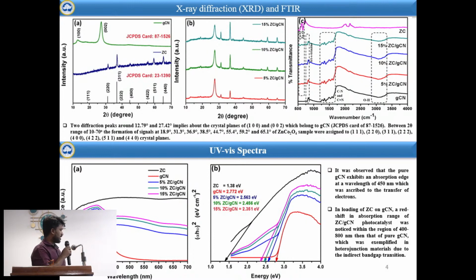And we have also obtained the optical property with respect to the UV analysis. We obtained the absorbance spectra, through which we calculated the Tauc plot, and from it we can obtain the band gap energy of the material. We calculated 1.38 electron volt for zinc cobalt oxide, 2.77 for graphitic carbon nitride, and a lowest of 2.351 electron volt for the highest composite sample, which comes under the visible light region.